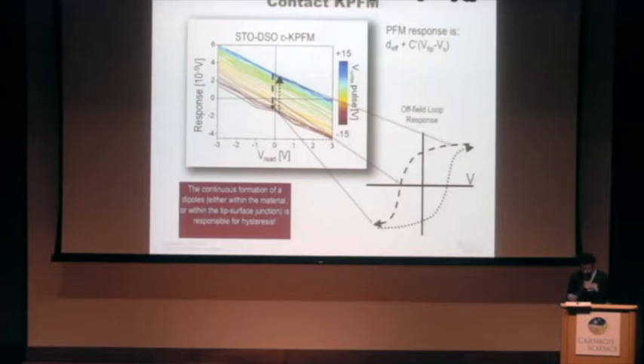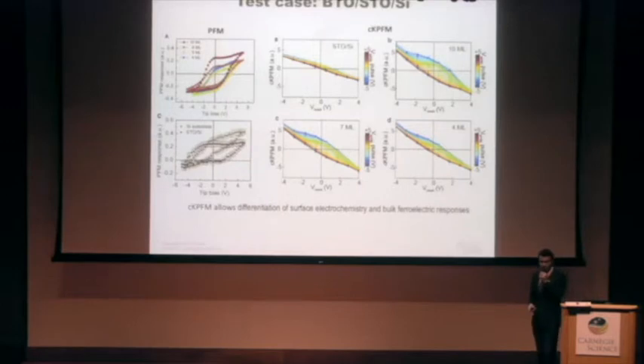So we wanted to see if we could measure this kind of dispersion in the ferroelectric states. To do so, we were very lucky to collaborate with Catherine Dubreuil, who is now in Berlin. She grew some barium titanate on silicon, and when we do these CKPFM studies, this is the STO on silicon. You can see it's pretty much flat. There's hardly any dispersion. In the 10 monolayer case, you can see one polarization state here and another polarization state here, and the width reduces as you make your barium titanate thinner. So this is the 10 monolayer case, 7 monolayer case, and 4 monolayer case. But still, you can see that there's a switchable polarization at 0 volts. It's kind of interesting.